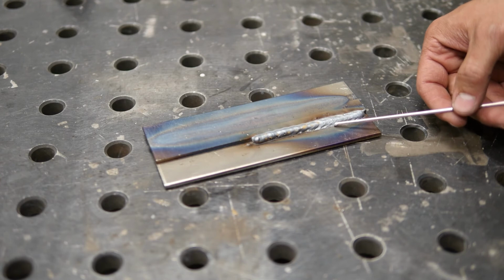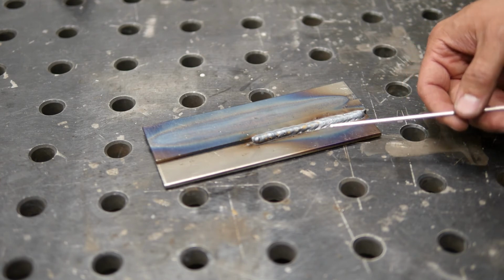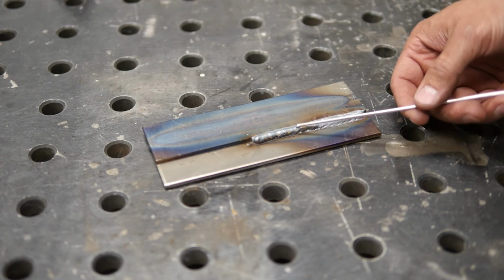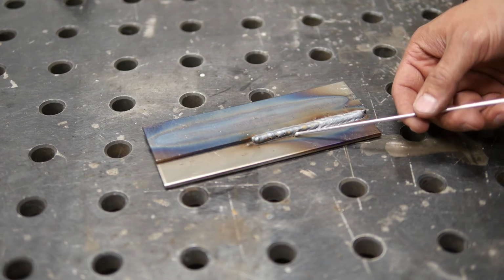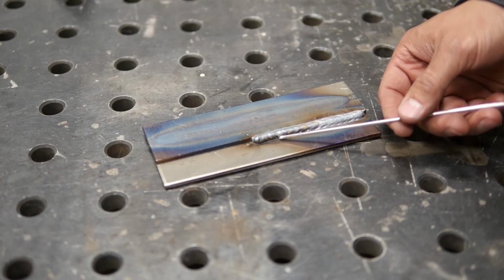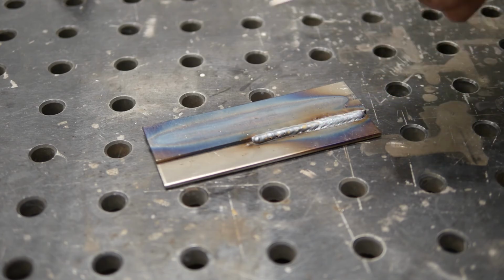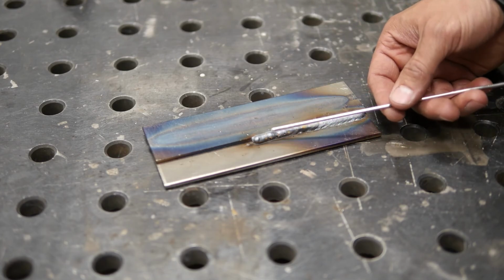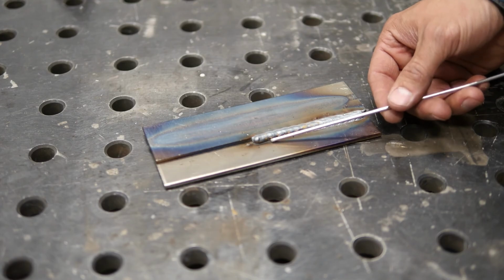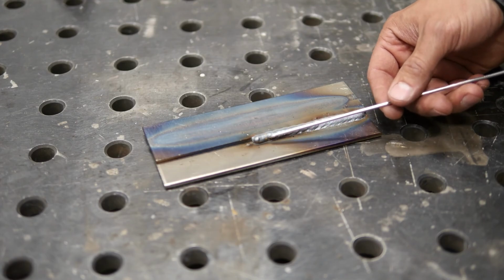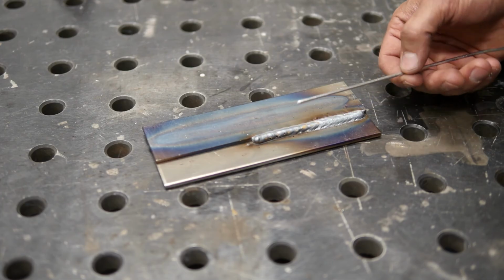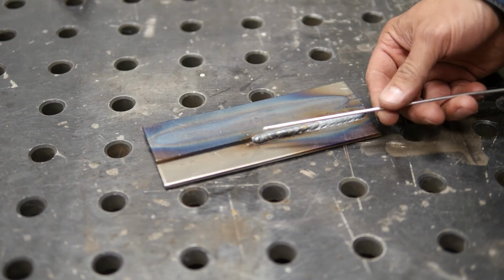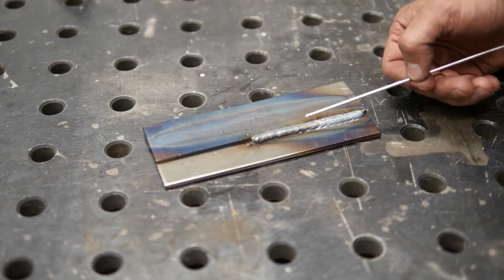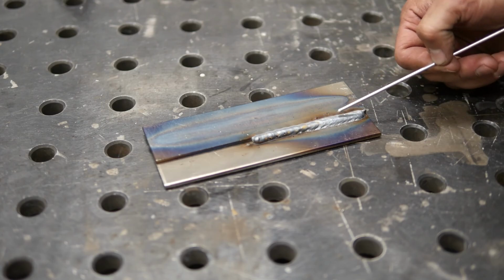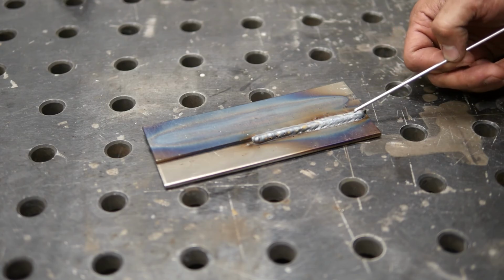It was started off pretty nice, and then I started to back the gun away, and then it started to lose amperage. So it started to lose punch in the material. And then about right here, right there, and right there, there's these little pinholes, and that's porosity. That's where the gas couldn't keep up, and we started to get the atmosphere sucked in there. That's not a good weld at all. There's iron nitrides in there, so we want to grind that completely out. We can't just weld back over that. So we've got to control that contact tip to work distance. It is a critical parameter.